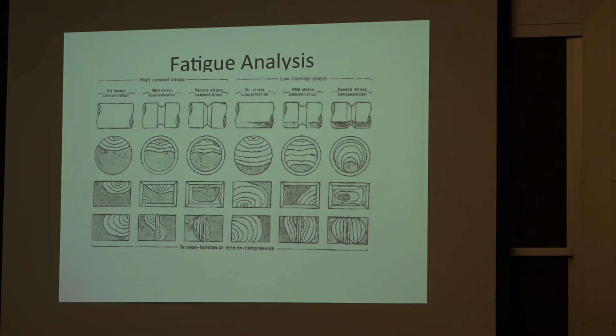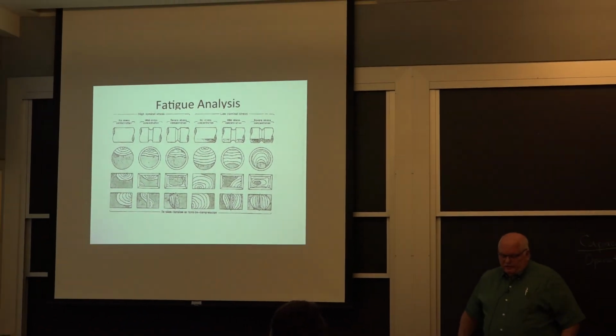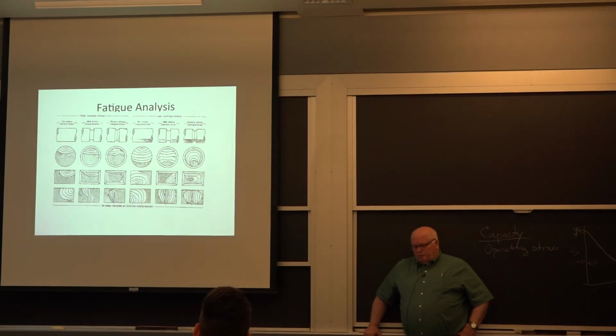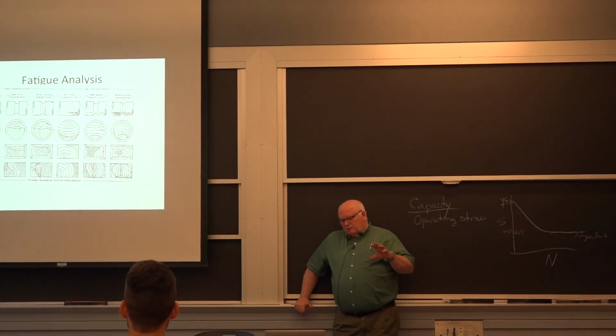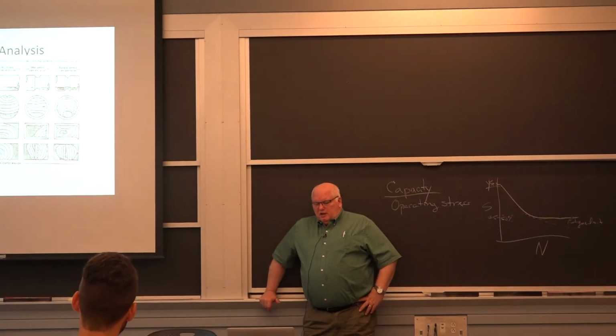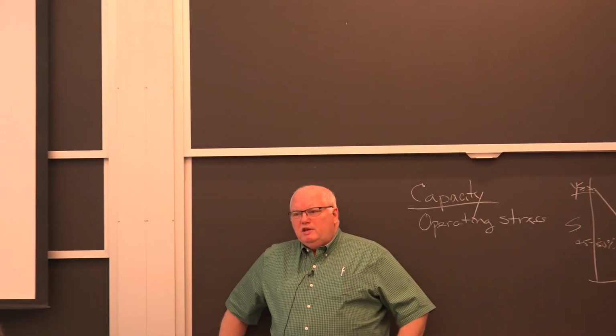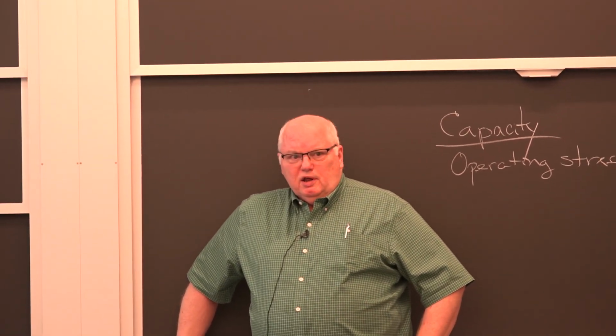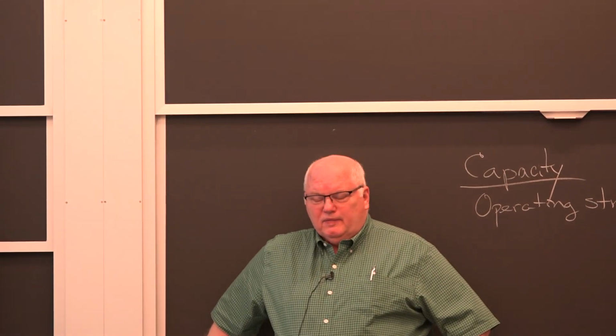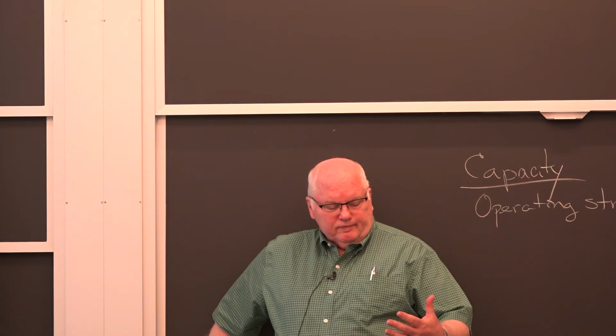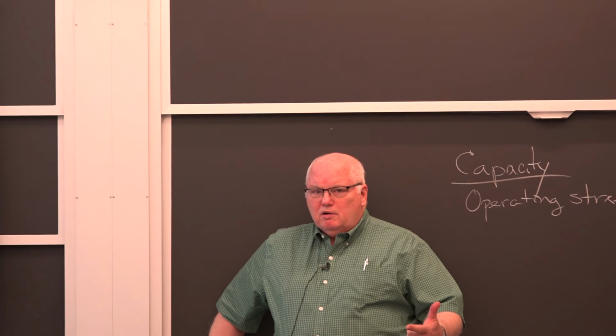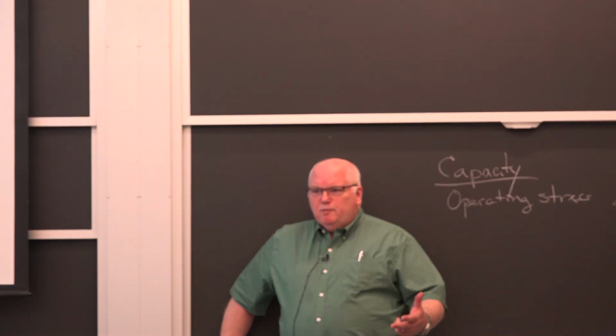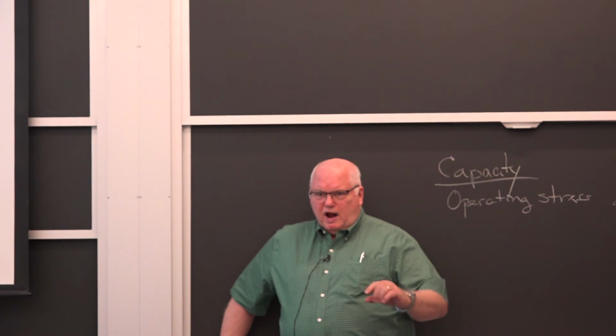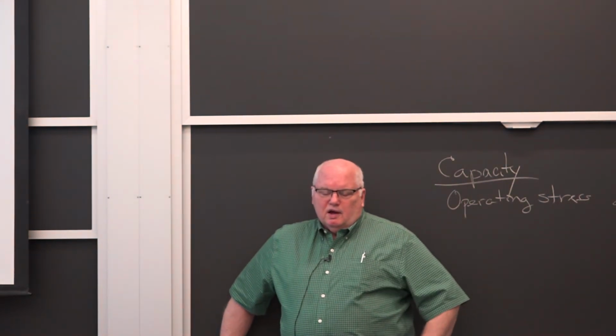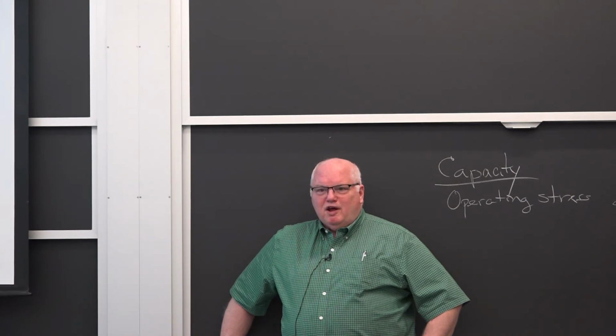In fact, back 30 years ago, a nuclear reactor had a problem on some of its bolts, and I was working for a test lab, this is the early 80s, and they said, we're going to send you a bolt, and we're not going to tell you anything about it. We want to know what you can tell us about it from just looking at it. So they sent it to us, and I looked at it and said, well, low cycle fatigue, moderate nominal stress, variable amplitude loading, because some of the fatigue cracks were different in width, showing how fast it was growing, and it was operating at 600 degrees Fahrenheit, and they were all surprised.